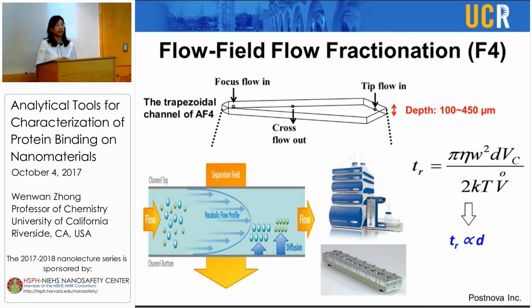So this technique separates things by their hydrodynamic size. For larger ones, because they diffuse slower than the smaller ones, within the parabolic flow profile inside the column, they will locate at a relatively lower level, so they migrate slower. But smaller ones diffuse faster, so their relative height within the parabolic flow profile is closer to the center, so they have a faster flow rate. They move at a faster rate, so they can come out earlier. So eventually those particles will be separated by their size.